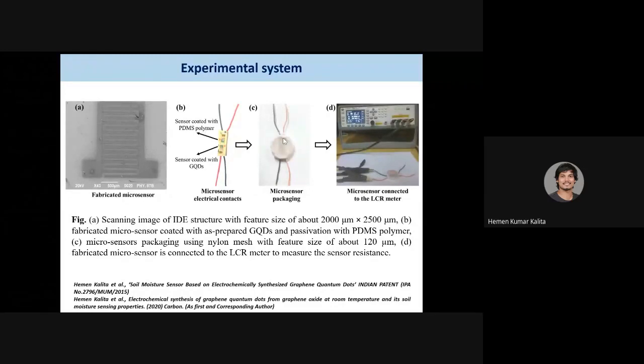We put a mesh on top of the sensor. This mesh is a nylon mesh, and the features are around 120 micron or so. This mesh is used because when we use this sensor for soil moisture, the soil should not come in contact with the sensor body. So only the moisture will come in contact. That's why, to protect the sensor, we have used a mesh. And this is the setup of how we measured the resistance with the LCR meter. So this is the microsensor setup we used in our experiment.